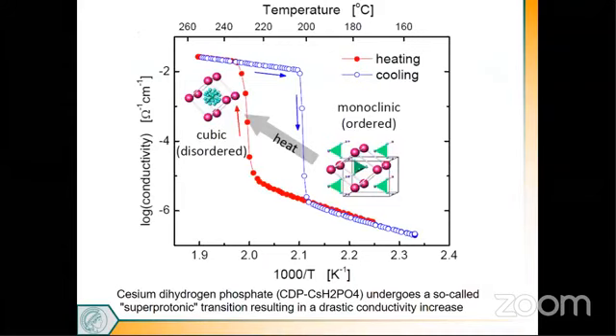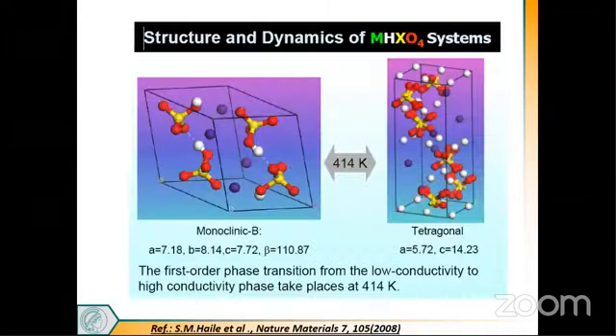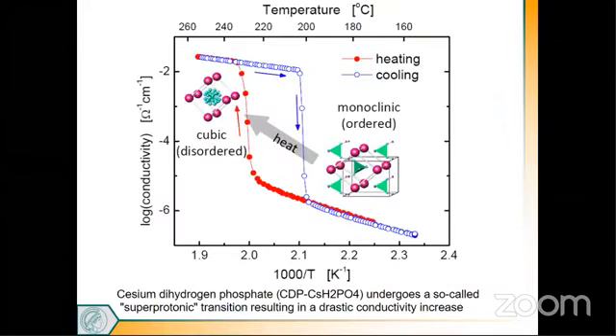That's what is happening basically. If you see, as we move from monoclinic to tetragonal phase, or even to cubic phase, there is a big jump in the conductivity accompanying the phase transition. This is an example for cesium dihydrogen phosphate. That kind of transition is called superprotonic transition. That results in a drastic increase in the conductivity, which is required for the operation of proton exchange membrane fuel cell.